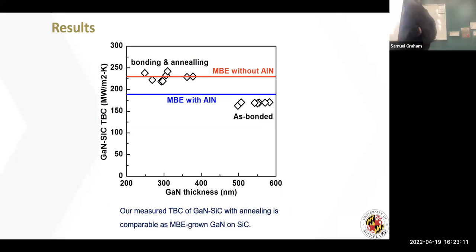Here's what we see. If I use a technique called molecular beam epitaxy and grow directly onto silicon carbide, so this is MBE without aluminum nitride, this shows you the thermal boundary conductance. So how well does that interface conduct? That's the best that we've seen in the literature. And you can see our bonding methodology actually matches that. It's a number of measurements across the sample, changing the sample thickness. This is as bonded. When we anneal and we crystallize, you can see that we get this very, very conductive interface, which is good. Someone may say, well, why not just do MBE? Well, there's an aspect of the throughput for commercial aspects.